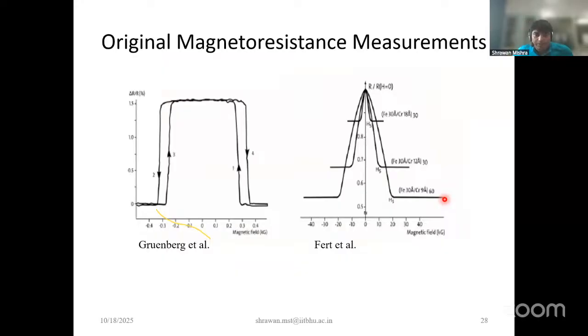And this is how their experimental data look. This is the first case that Grünberg reported: if you have the magnetization in an anti-parallel configuration, you have a very high resistivity. But when you go to the saturation side, the negative saturation side, the resistivity is an order of magnitude smaller. So in the same material you can generate two resistive states. That's very much like our electric switch, which we use in our daily life in our houses. It's the ability to turn on and off. So the high resistive state is off and the low resistive state is on.